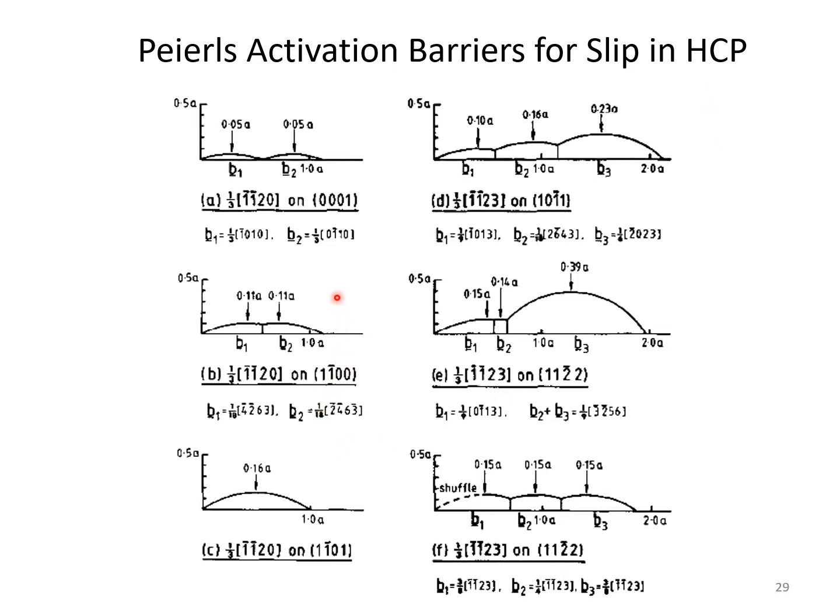So the case when it comes to hexagonals, the case I just talked about, which was for the face centered cubic, is the same case for the basal plane in hexagonals. You get these two partials in the Miller-Bravais notation. These are the partials. So we have these low energy, easy routes to translate a full Burgers vector, 1/3 <11-20>. In order to get from here to here, we go through a two-step process, which isn't exactly aligned, but it's a little jog off one off the other. And that's in the basal plane.